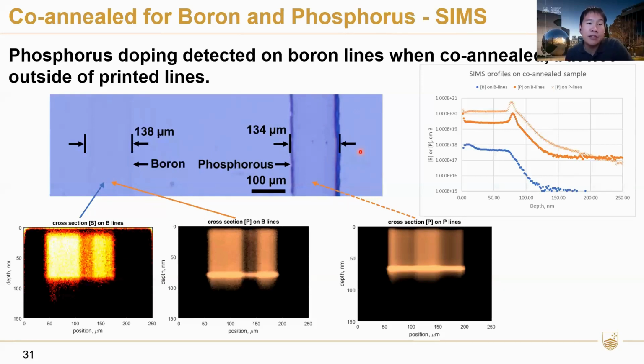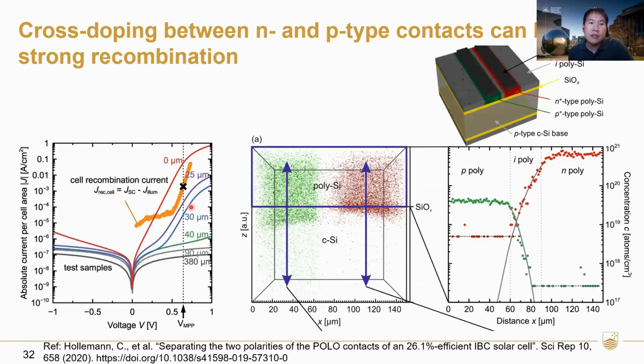This is bad news for us because we want to have one N-type and one P-type line. The PR shows that it is effective, but the SIMS clearly shows that it's not. We have some issues there. And the main issue is not only that it's completely compensated, but it's also an issue if those two lines start touching, and then they will form a PN junction, which creates a really, really high recombination area.